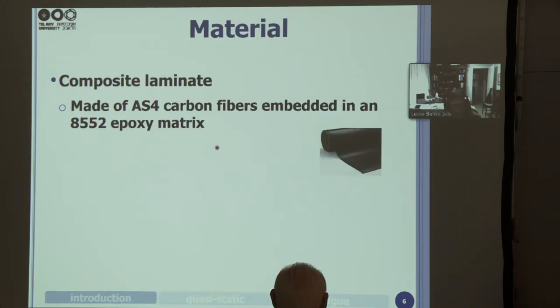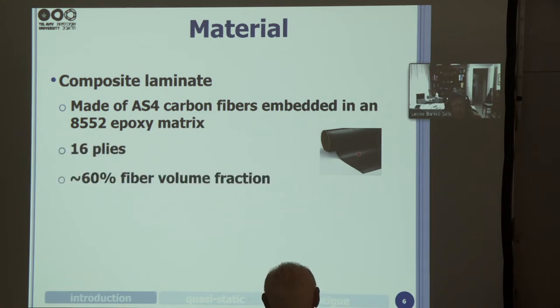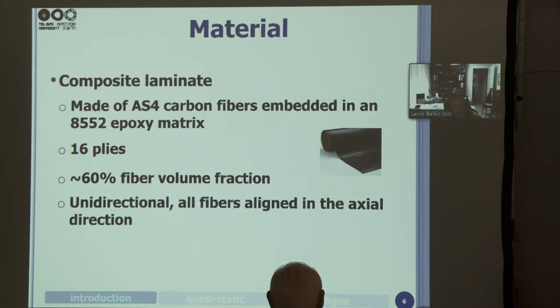And the material that we're using is a laminate, and it comes, as you can see on the right, as a prepreg. It's made of AS4 carbon fibers, which are embedded in an epoxy matrix. The epoxy is 8552. There are 16 plies in the specimen. The fiber volume fraction is approximately 60%.